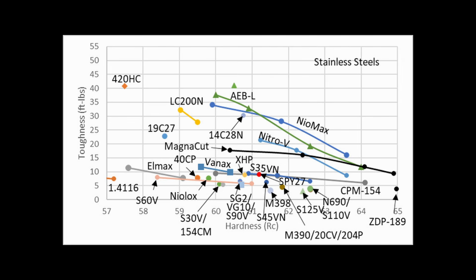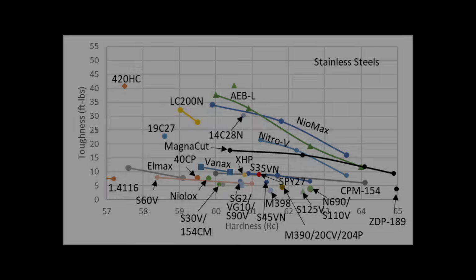There might be some caveats, such as if the steel were being heat treated with a relatively slow quench and without a cryo treatment and tempered at 400 degrees, perhaps it might drop into the 58 to 59 Rockwell C range without negative effects. It wouldn't be 100% optimal, but I wouldn't call it improperly heat treated.